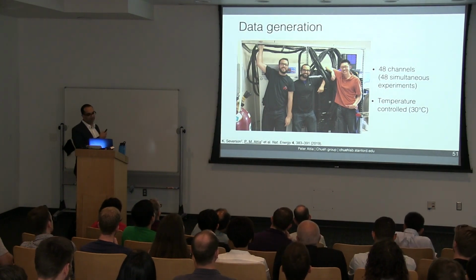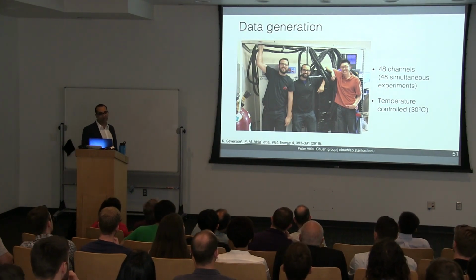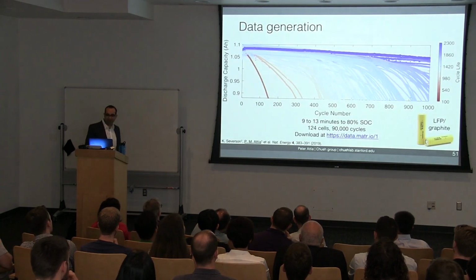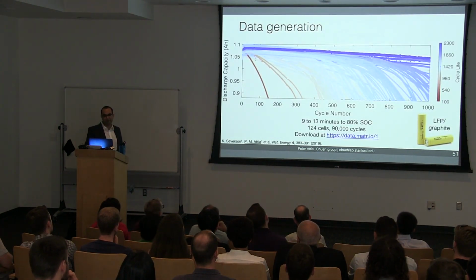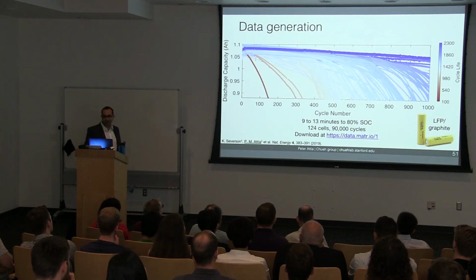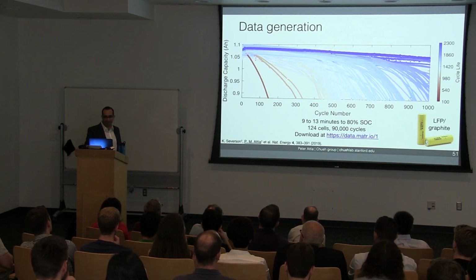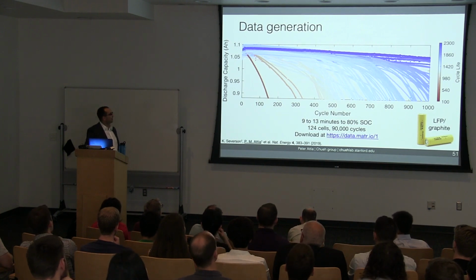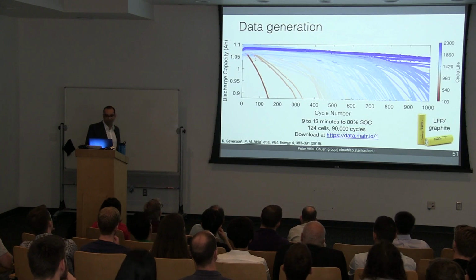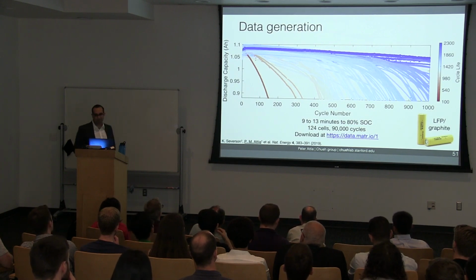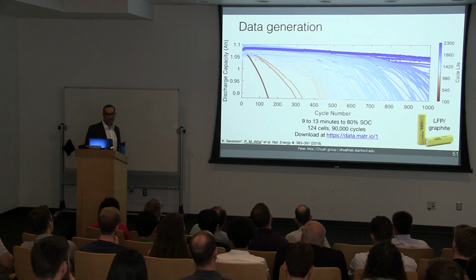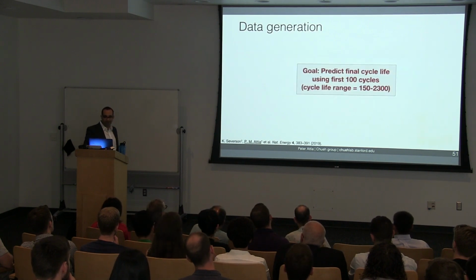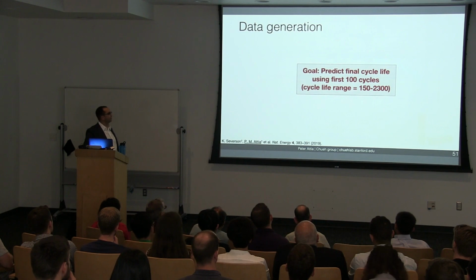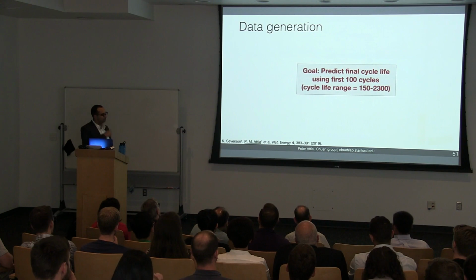So the first step in this process was setting up the cycler. We have a 48-channel battery cycler, and we cycle the cells in a temperature control chamber. We then generated a data set of 124 batteries cycled to failure during fast charging. We cycled the cells with a bunch of different fast charging conditions, but we kept the discharging conditions fixed at 4 C. What we found is that the cycle life is highly sensitive to the charging time. The charging time here varied from 9 to 13 minutes, but this small difference in charging time has a massive effect on lifetime. So again, the goal of this work is to predict the final cycle life using the first 100 cycles. And here the cycle life ranges from 150 to 2300 cycles.